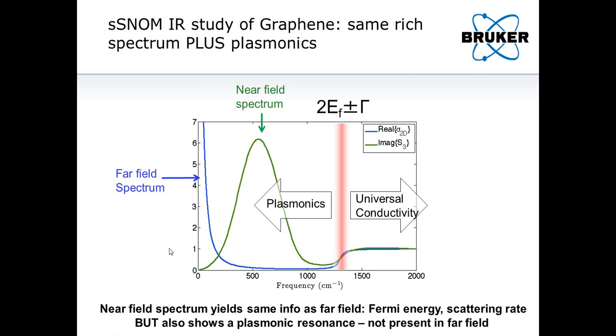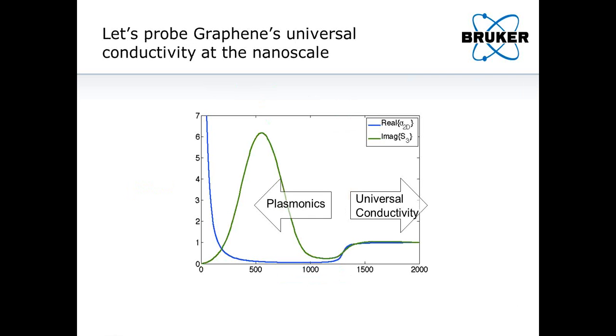So let's look at some experimental results first in the universal conductivity regime. We set our IR frequency to about 1730 wave numbers, and this should fall in the universal conductivity regime, provided our Fermi energy is not too high.